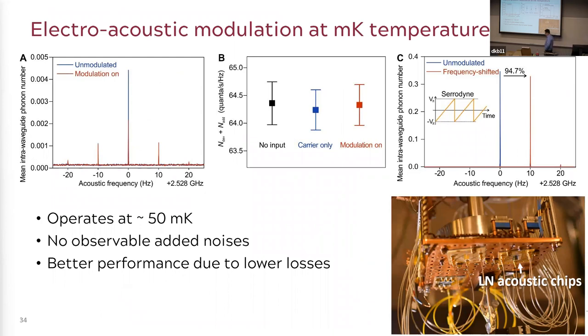Then I want to mention, I discussed the mass of our device at low temperature, but also the modulation. Does the modulation only work at room temperature? If you ask about the thermal approach, yeah, probably. At low temperature, you cannot apply a heater to heat up, right? Otherwise it won't work. But luckily, our acoustic approaches, as I mentioned, do work very well at low temperature. This is what we do. Because at low temperature the signal is so small, we can only measure the sideband powers. On the waveguide, the modulation still happens.